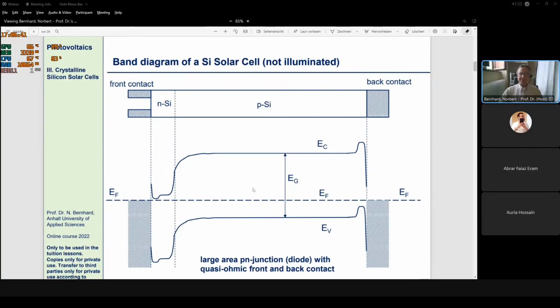In the lowest picture, we see the conduction band edge and the valence band edge. And as a dashed line, we see the so-called Fermi levels. The Fermi level is just that energy at which the occupation probability of a state is 50%. Roughly, it just separates the occupied from the unoccupied states. This is clearly visible in the metals. You see the metal band is filled up to the dashed line, and above it, it's empty. In the semiconductor, it's a little bit more complicated because here the Fermi level is in the band gap. Therefore, of course, we need to have this view of 50% occupation probability if there would be a state.